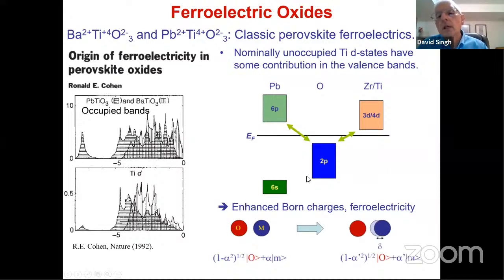And the way it works is like this, you have some 2p states of oxygen that are occupied. It's nominally oxygen 2-, and then some empty states on the metal atoms, lead and titanium, that are cations. So these are, for example, the 6p state of lead, which is not occupied. The 6s state of lead is occupied. It's lead 2+. And so that's the ionic story. But then there is some covalency, some hybridization between the oxygen and the lead.